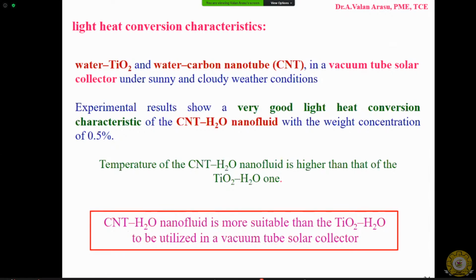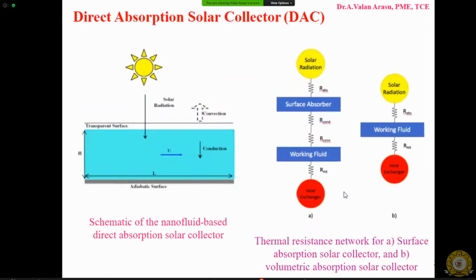Okay. So the efficiency of this collector was experimentally studied using nanofluids, water titanium oxide and water carbon nanotube nanofluids. It was found that the carbon nanotube based water nanofluid has very good heat conversion characteristics. So the temperature of the water obtained from this CNT nanofluid is higher than that of the titanium oxide based water. So this study confirmed that CNT-based water nanofluid is more suitable for vacuum tube solar collector applications.